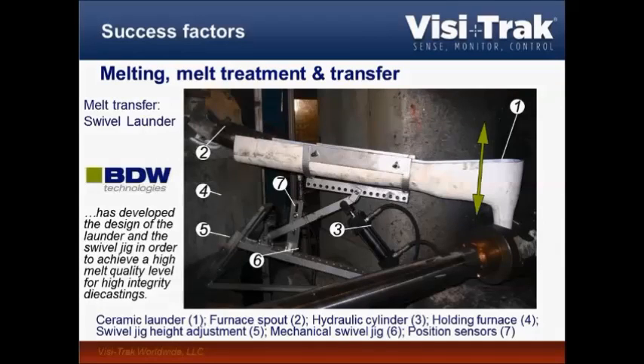BDW actually went even further, and they said we need to get rid of all the oxides before we get the metal into the shot sleeve, and they developed their own little, what they call a swivel launder, and this is a simple launder that actually moves downward and puts the metal nicely on the bottom of the shot sleeve, which eliminates, of course, all the turbulence that you would get, but B, also helped extend the life of the shot sleeve by a factor of about 10. And when you use basically primary structural alloys, that really goes a long way because they are very aggressive both on the dies and on the shot sleeve.